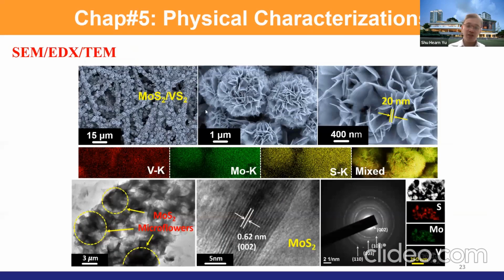All right, so this is the structure of MoS2 and then VS2. The VS2 is underneath, you cannot see it. It's fully covered by the MoS2. I find that under SEM, this is about 20 nanometers in thickness. And then we do EDX testing. We have vanadium, molybdenum, and sulfur. When I mix these three figures together, I find that the vanadium, which is the red color one, is uniformly distributed over the MoS2.